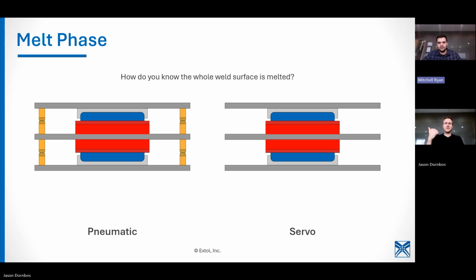And we can monitor the force being applied. So if for some reason the force drops off, that is a flag. The machine can flag that and say, we didn't hit the amount of force we usually see to melt this part. My guess is that something is wrong with your part. Maybe there's a big short shot, or the parts are shorter for some reason, and it's not melting the entire surface because we didn't use the amount of force we needed.